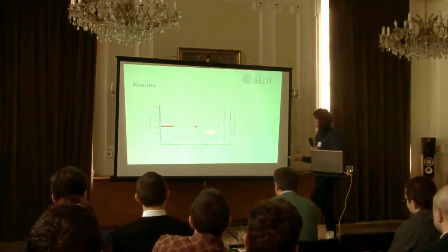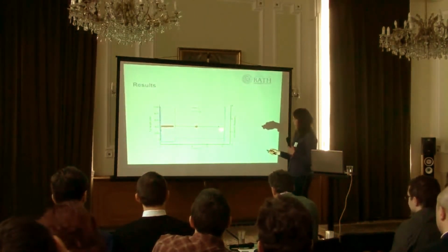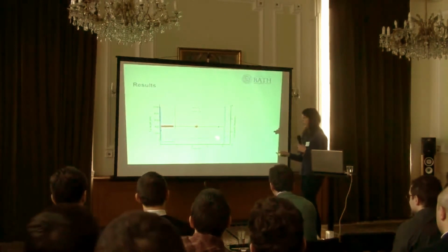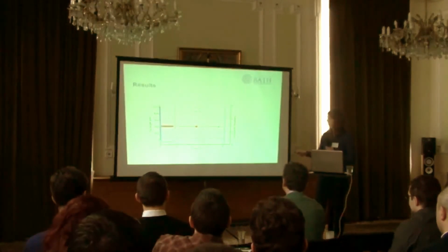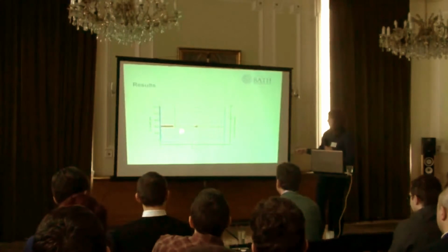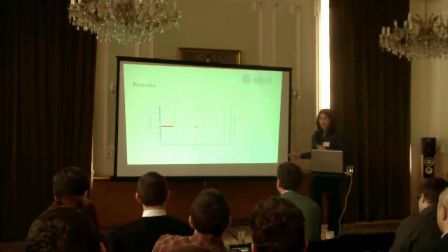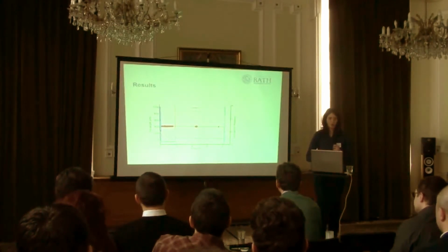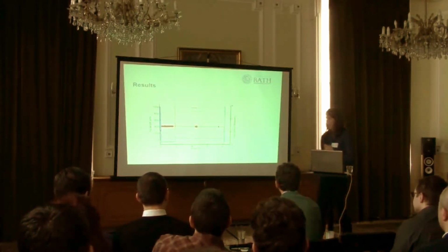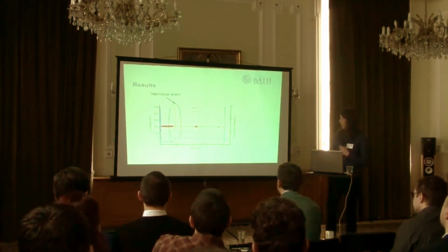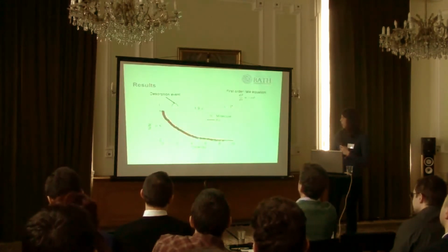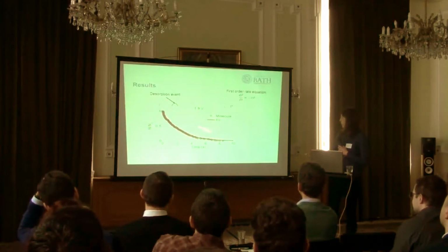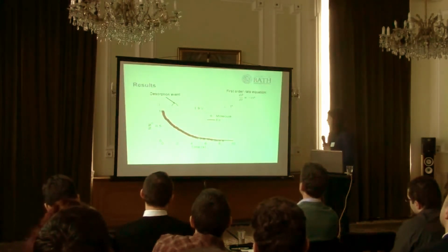The information that we get from this is that we've recorded the time, current and height of the STM tip, and essentially this tells us when the molecule has left the surface. So we know exactly how many electrons we have injected into that molecule before it has left the surface. Doing this a lot of times gives us a nice solution to a first-order rate equation. Essentially each one of these spots is an individual molecule that we have manipulated.